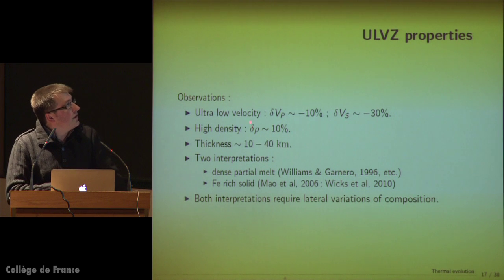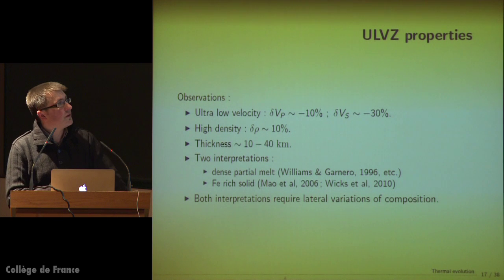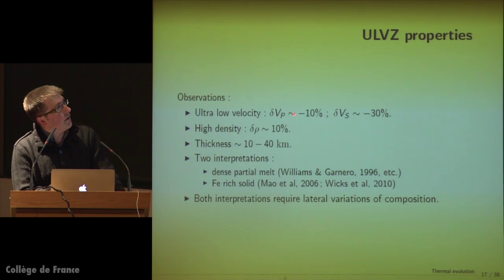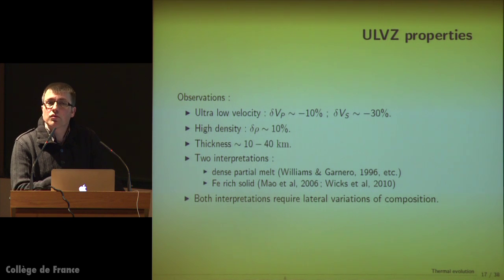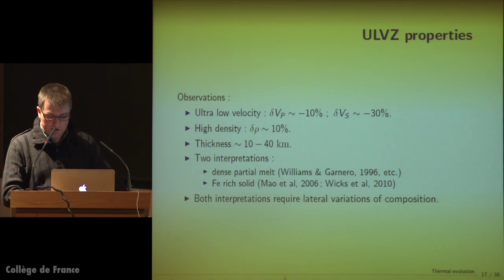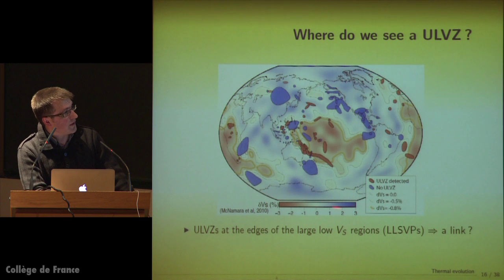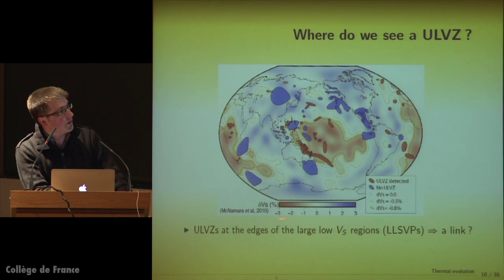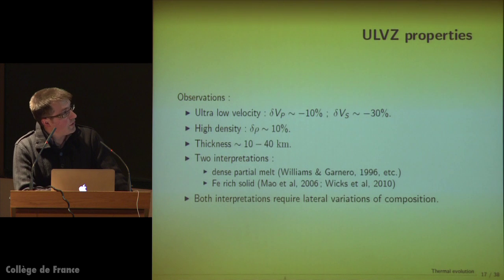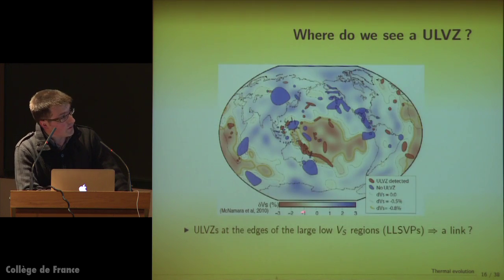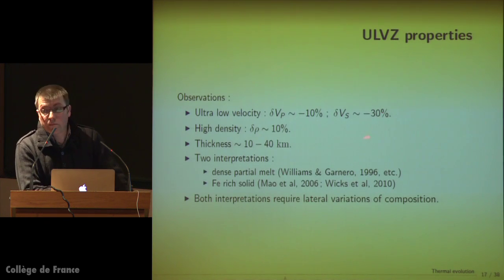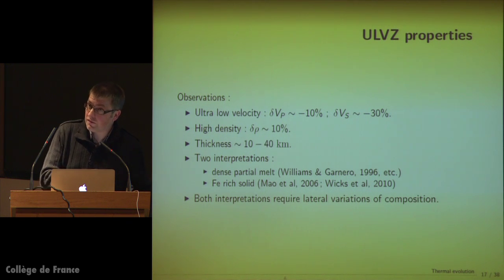And what are these ULVZs? Just to sum up, what seismologists find is a delta VP of about minus 10%, which is a big number compared to the kind of number that we discussed before on the large-scale velocity variations. If you compare with here, for example, the tomography map is between -3 and +3. Here, that's for VS, of course. And so for VS, you get minus 30% in ULVZs, so that's a very big number.